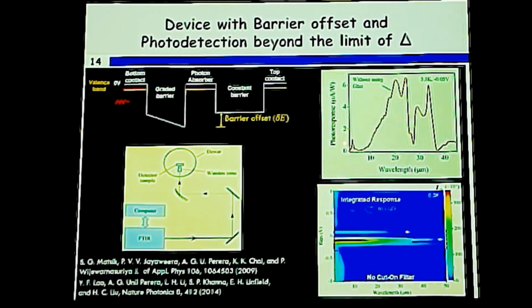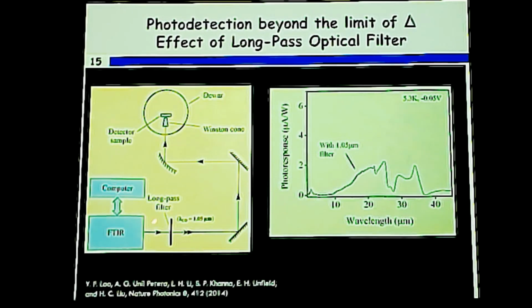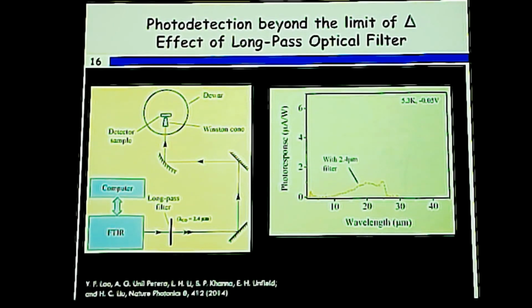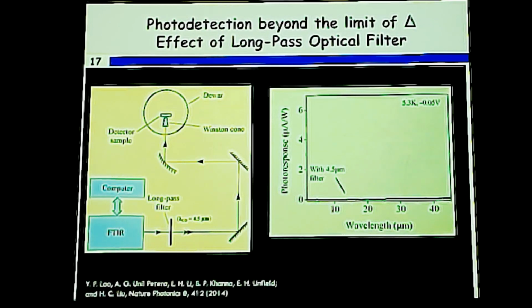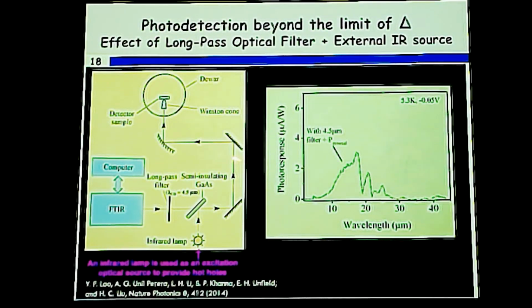For example, if we block high energy radiation around that region, that extended wavelength photoresponse disappears. So what we do is we put an optical filter which is transparent beyond a certain cut-on wavelength, but shorter wavelengths are blocked. So you see the extended wavelength response became weaker. With a longer cut-on filter, it becomes further weaker. With 4.5 micron, it is mostly gone. However, with an external source of infrared radiation falling onto the detector, that extended wavelength response is recovered. So this means that some high energy infrared radiation is necessary for this kind of mechanism. That was the finding.